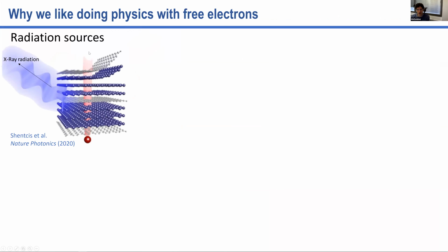And I want to bring a few examples throughout this talk of the kind of experiments we can do in microscopes of this type. And one example is that we can use the electrons to generate radiation. And that is, of course, very well known in cathodoluminescence, but also in EDS, in X-ray spectroscopy. And what we did here is that we used the microscope as a way to extract efficiently X-ray radiation. We're using van der Waals materials. So that came from a few collaborators, most of them from the group of Efrat Lifshitz at the Technion,